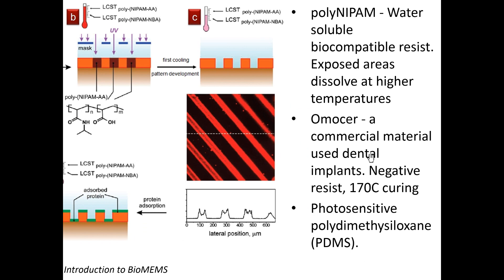Other examples of biocompatible materials include one that is commercially available and FDA-approved as a dental implant material. It's essentially a UV-curable acrylic type material — a negative resist meaning that regions exposed to light cure — and you also have to heat it to 170 degrees Celsius. There is also photosensitive PDMS, polydimethylsiloxane, which is a very popular material used in microfluidic devices and will be discussed more later.